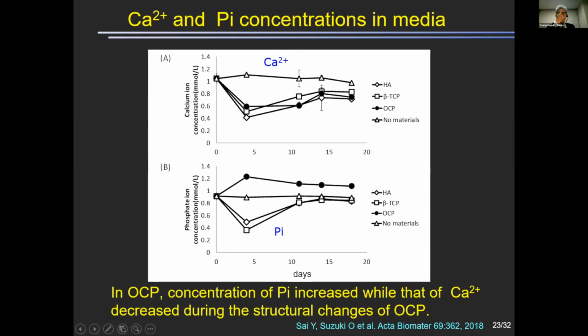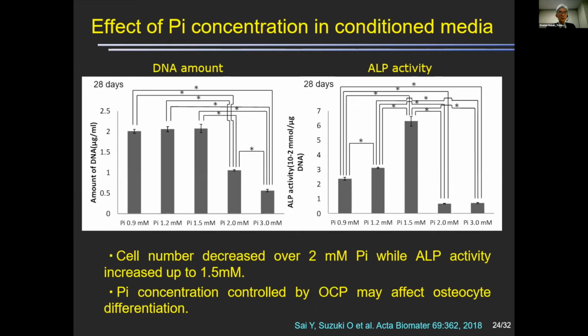So we pay attention to the phosphate ion in the osteocyte differentiation. This figure shows the effect of phosphate ion concentration in conditioned media in the absence of OCP materials. This is just the effect of phosphate ion concentration. And with increasing phosphate ions, the ALP activity increases up to 1.5 millimole. That decreases over 2 millimole. So this investigation suggests that the phosphate ion concentration controlled by the OCP materials may affect osteocyte differentiation.